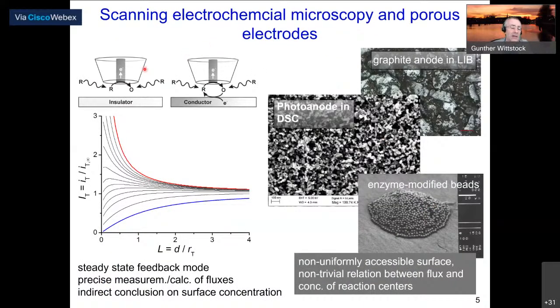Okay, so here we see a little bit on how that can be done. This is this microelectrode. It makes an electrolysis of a compound that can be oxidized. I typically use in these schematics generic symbols like R for an oxidizable compound, the reduced form, and O for the oxidized form of a redox couple. And if we make this electrolysis and the microelectrode is close to an insulating surface, the presence of that surface hinders the mass transport of that reactant to the microelectrode, and the current goes down the closer we come to that insulating surface.